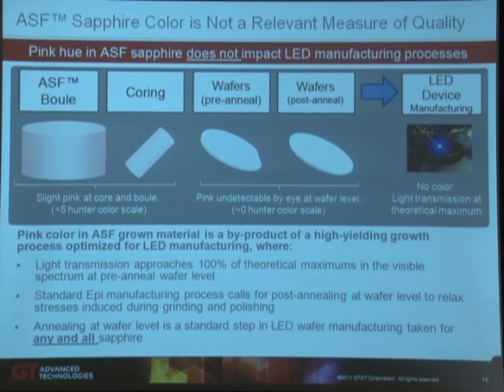If you look at the standard wafering process at all the major wafering houses, the core material from the original boule is sent through the sawing wafering process and goes through an annealing process to reduce the stress that is imparted during that. What we were able to find was that the pink color in the ASF grown material is a byproduct of a high-yielding growth process optimized for LED wafer manufacturing, where light transmission approaches 100% of theoretical maximums in the visible spectrum at the pre-anneal wafer level. Standard epi manufacturing process calls for post-annealing at the wafer level to relax stresses induced during grinding and polishing. Annealing at wafer level is a standard step in LED wafer manufacture, taken for any and all sapphire.